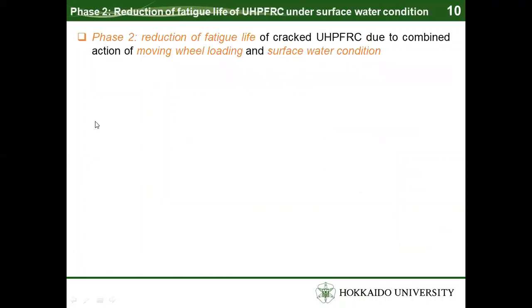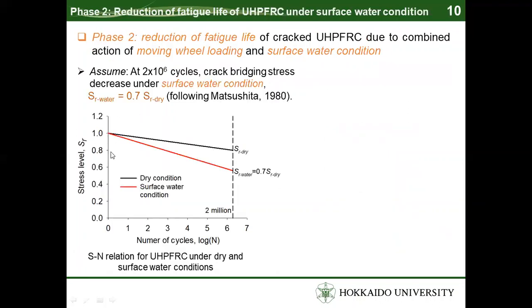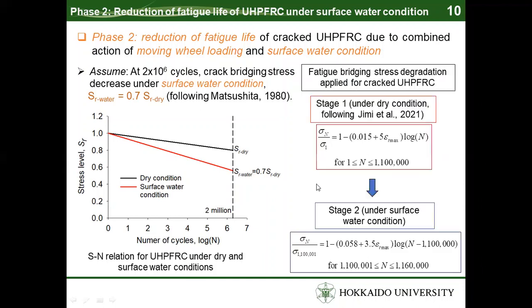For phase 2 of the material model, it is assumed that at 2 million cycles, the stress level in water conditions is chosen as 70% of that from dry conditions. And the bridging stress relation applied for the cracked UHPFRC under surface water conditions in stage 2 can be calculated as shown in this equation.